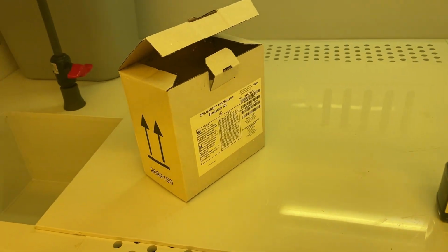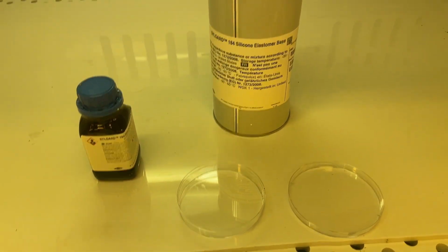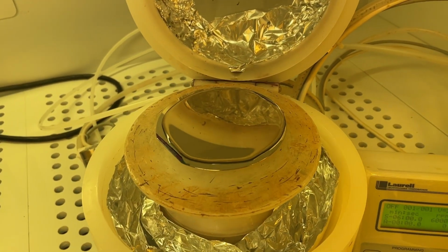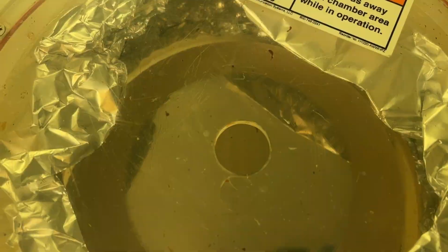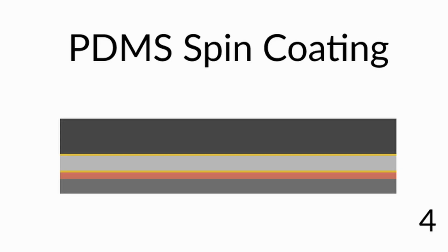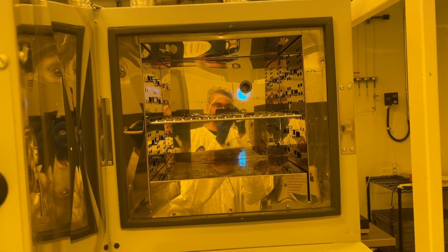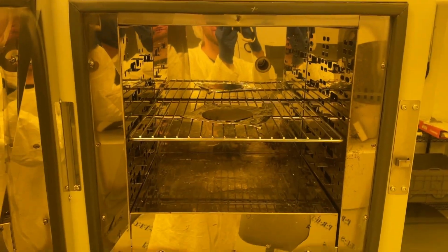Next step was the PDMS spin coating. I mixed the Sylgard 184 monomer and curing agent in a 10:1 ratio, then degassed the mixture in a vacuum chamber. I added it to the wafer and spin coated it at 6,000 RPM for 5 minutes. This should have resulted in a 5 micrometer film. Then I cured it in the oven for 15 minutes at 150 degrees.